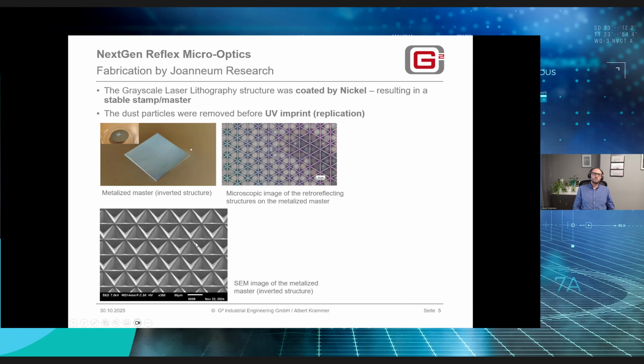Also for this process step, after the nickel coating, an electron microscope scan was done to check the quality of the surfaces, and what we could observe already here is that the radius increased during this nickel coating. But that was something we expected, so nothing dramatic in theory.